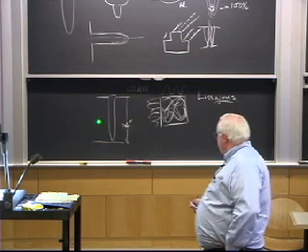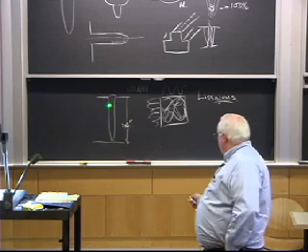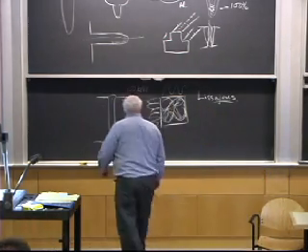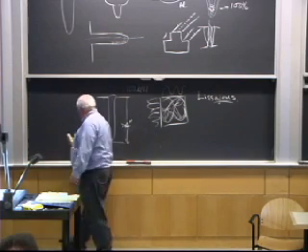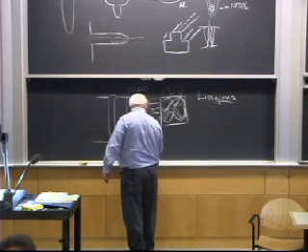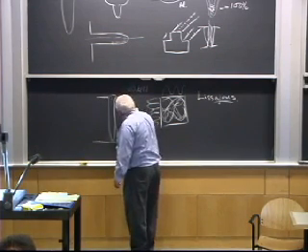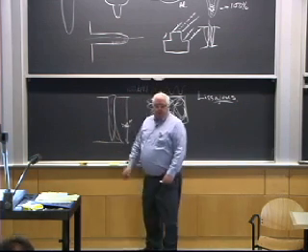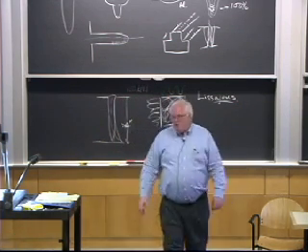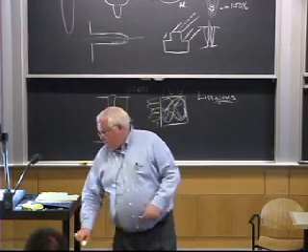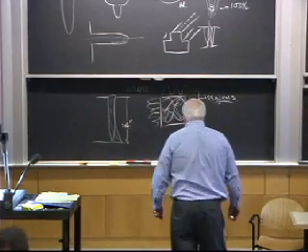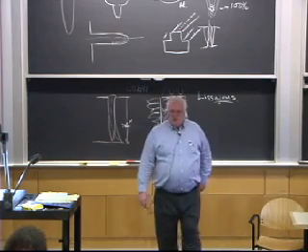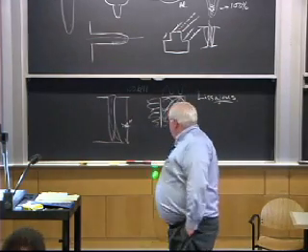So if I have a high magnetic field over here on your left, the beam will actually distort to the right, and the thing will actually come like this, and I'll miss my joint at the bottom. Well, that's okay. You can demagnetize your steel, although it's 8 inches thick and weighs 50 tons or 100 tons. It's not the easiest thing to manipulate, but you can do that.